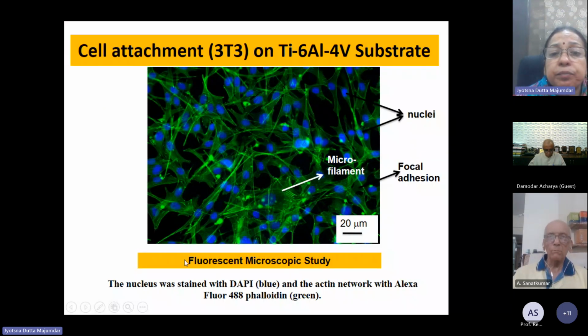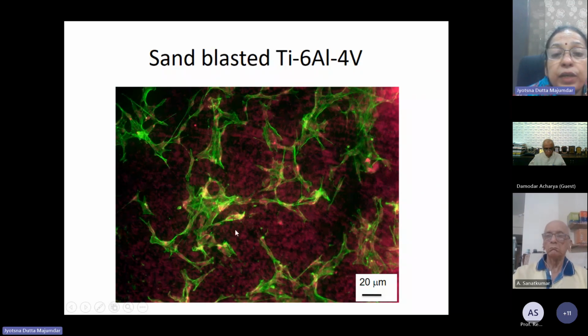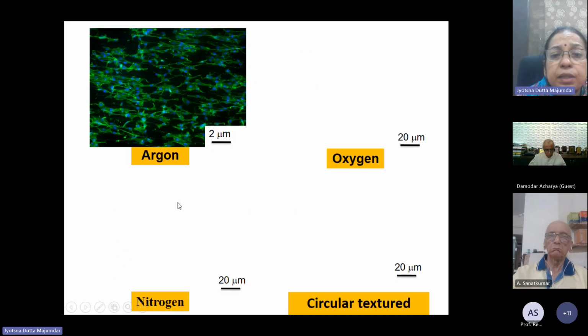This is the typical cell attachment behavior of the as-received sample, where we used 3T3 cells as the cell media. It was random but uniform all throughout. But when we compared it with sandblasted samples, people use sandblasting, but attachment was not very strong and uniform, and the percentage of cells adhered was also much lower than that of the as-received samples.